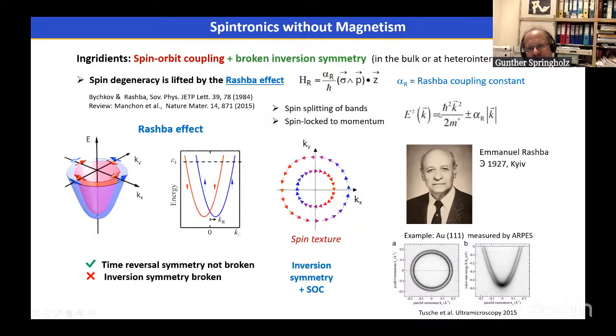For a free electron system and for a linear Rashba effect, the energy momentum dispersion is then shown here by this equation. So we have the free electron term h squared k squared over 2m plus minus alpha times the momentum of the electron, the absolute value of it. So that means this equation defines the two terms. Each one is parabolic, but is shifted by this Kr value.